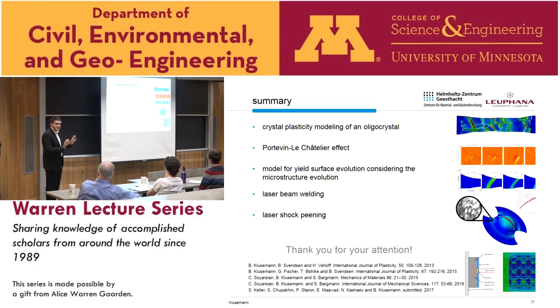Oh, actually, in this case, we didn't try anything before, because what we used is a very classical crystal plasticity model. This is known since the 90s, I would say. We were actually impressed that we could capture this already with this simple model. We were expecting we would need something much more sophisticated to accurately predict this kind of deformation history, but fortunately we had to say no, we don't need to do any GND kinematic hardening. The simple crystal plasticity, which mainly accounts for the Schmid stress, that's the main contribution, is already enough.